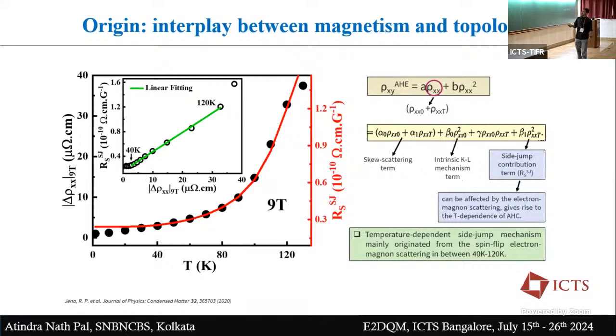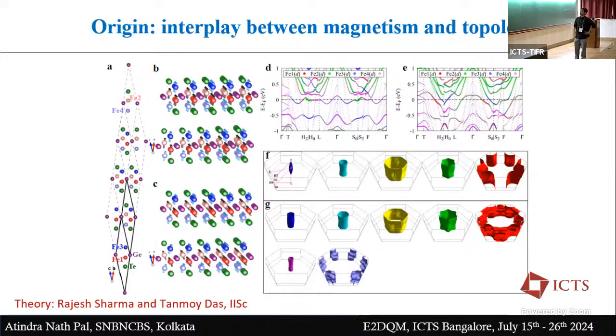But what we feel is that we have a strong electron-magnon interaction in this region, and this anomalous Hall effect also has a dependence on the side jump mechanism, so it will not be solely from the intrinsic origin. So the temperature dependence of the anomalous Hall conductivity also comes from the extrinsic origin. I'll not go into the detail. We have done a detailed analysis of this data, and we actually gave the different components from intrinsic and extrinsic origin in our work. Then we talked to Tanmoy for understanding these Hall data.